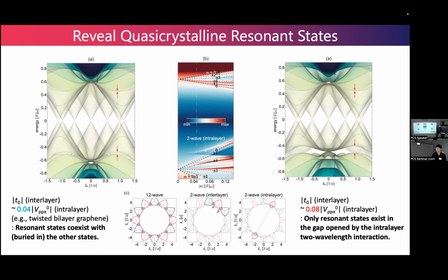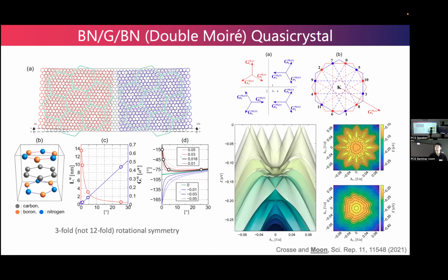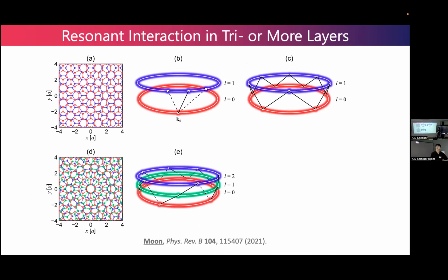However, if we increase the interlayer interaction, for example, by applying pressure or using another material with larger interlayer interaction, then the intralayer interaction opens a gap throughout the Brillouin zone and excavates the resonant states. So it would be much easier to observe, and also to investigate the double moiré structure. But yeah, this